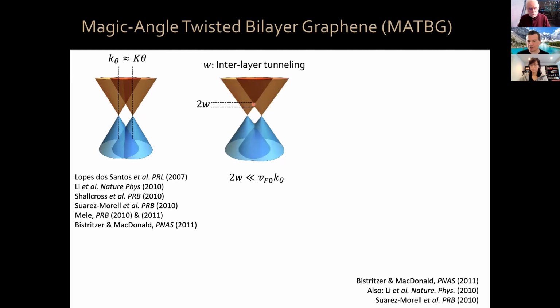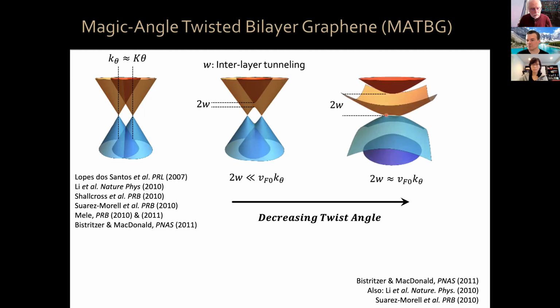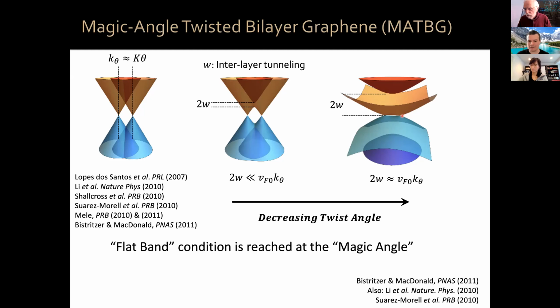Now, the situation here is realized when this interlayer tunneling is much smaller than the energy of that crossing point. However, as you decrease the twist angle, these 2 Dirac points get closer and closer, so this bonding band gets pushed down to lower and lower energy until it gets pushed down to 0 energy, okay? When this is realized, we say that a flat band condition has been reached, and this occurs at the magic angle. That magic angle value for graphene on top of graphene is 1.1 degrees, okay?